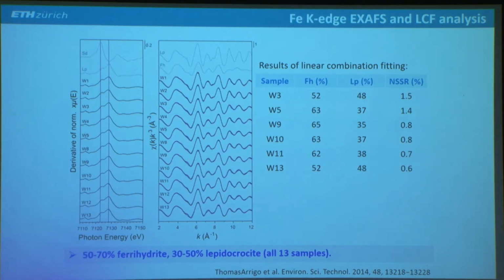If we look at iron EXAFS of these flocks, again, you can see these are many different flock samples. The spectra look all alike, meaning that the iron speciation in the flocks is also very similar between the flocks. There's not so much variation. And all these spectra can again be explained by 2 references: ferrihydrite, a very poorly crystalline iron-3 hydroxide, and lepidocrocite, the top spectrum.